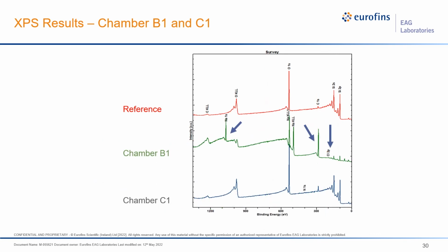So chambers B1 and C1, which were in the other laboratories, have also some things that we see in the XPS that are not present on the reference chamber. The chamber B1 has a strong sodium peak. You can see that out here. There's a very large sodium peak along with a chlorine peak. And sodium and chlorine, along with a much larger carbon peak, scream of handling, right? That's somebody's fingerprint. So that's what's going on in chamber B1. It probably has some handling issues there. And that may be handling of the wafer by the person putting it in and out of the chamber, or it could be from the chamber itself, just needs some cleaning to get rid of sort of the human residue.